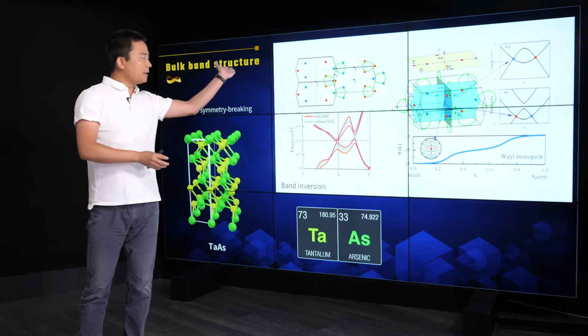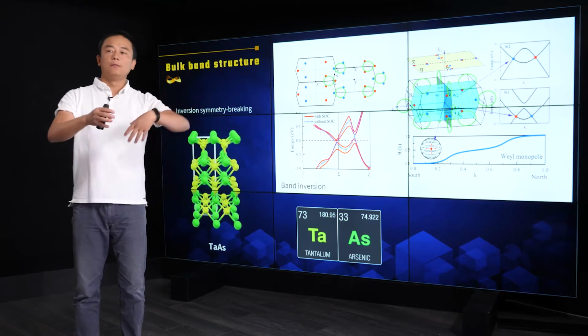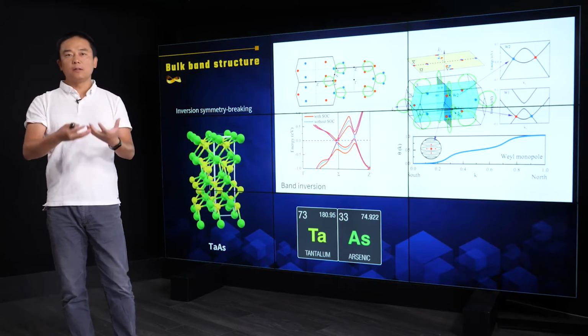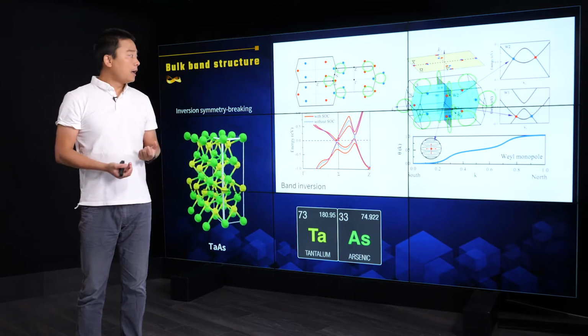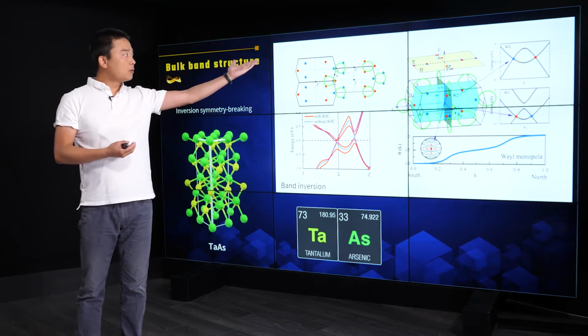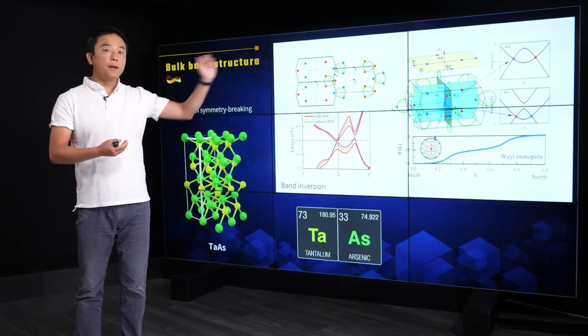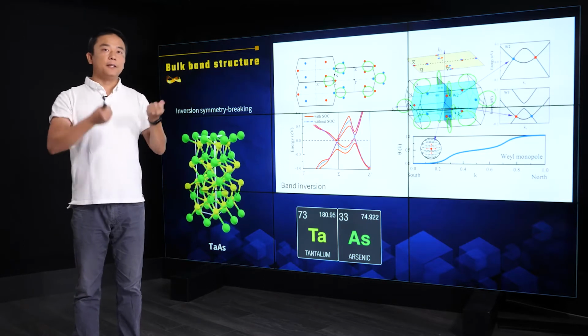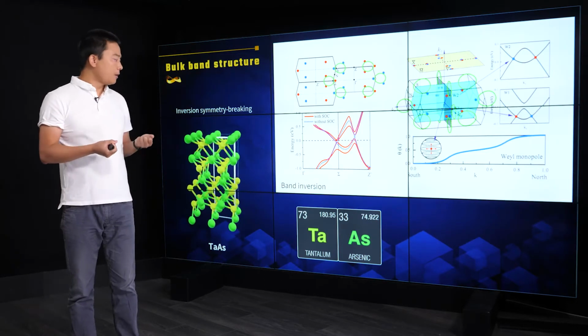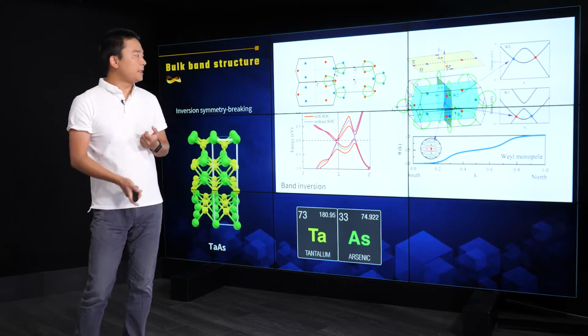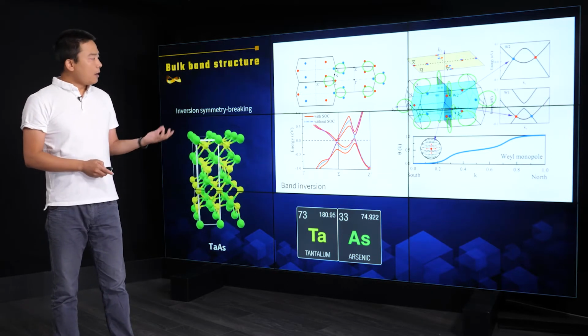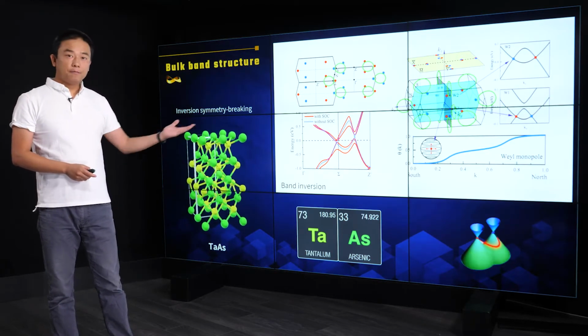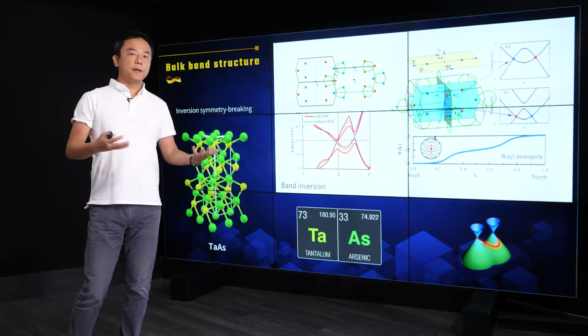If the dispersion is opposite, from 1 to 0, it has a negative topological charge. And these pairs, this green, this blue and red pair, always have opposite topological charge, or we call it chirality, opposite chirality. This Weyl monopole has a consequence: the surface Fermi arc, a special surface state.